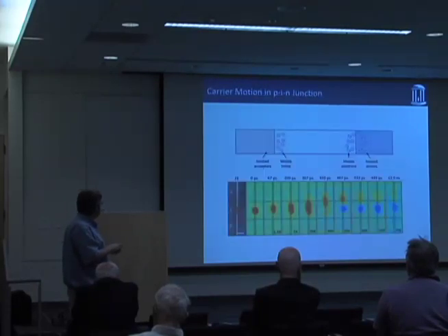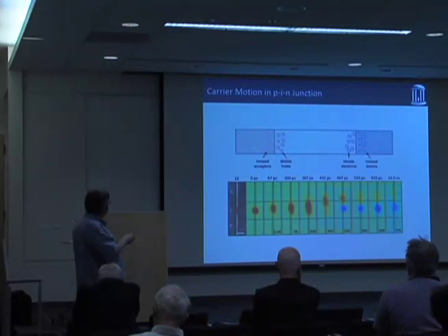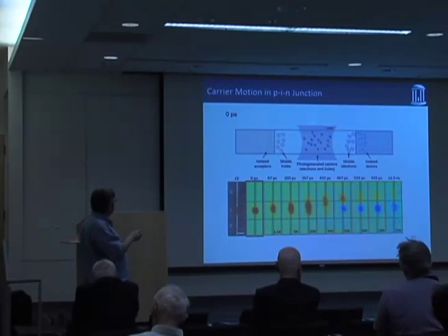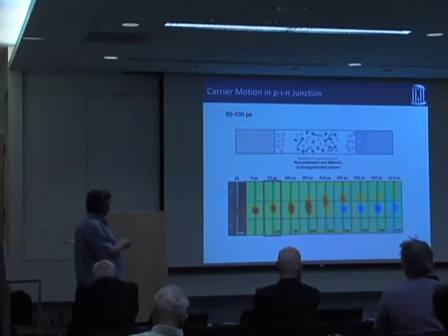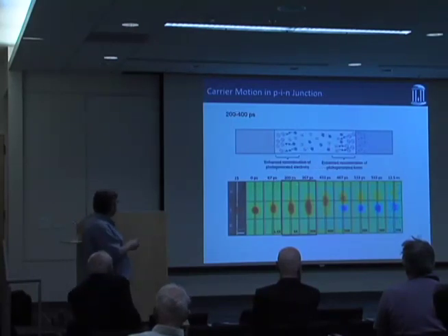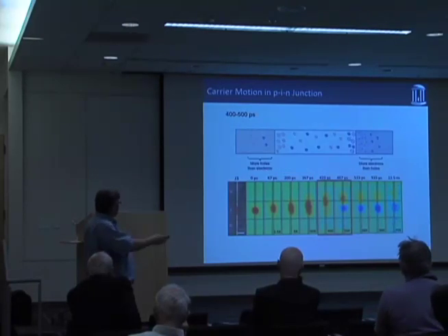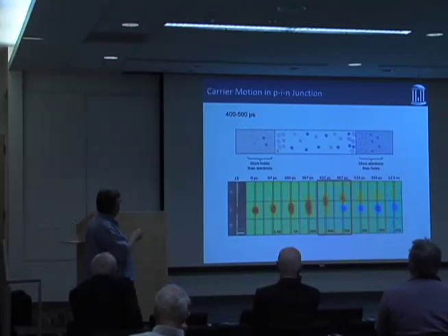And so to go back to our data here, here's this scheme I put up early on. At t equals 0, we come in and create a bunch of carriers in the middle of this intrinsic region. Over the first 100 picoseconds or so, that charge cloud expands. By about 200 to 400 picoseconds, it starts interacting with the mobile carriers that have accumulated near the boundaries. It spills over into the n-type and the p-type regions, but now on one side you have more holes, on the other side you have more electrons.